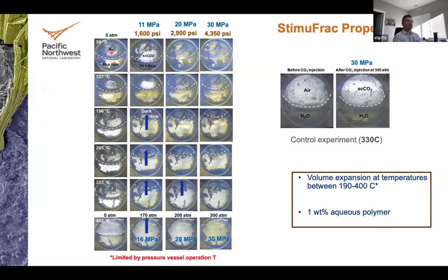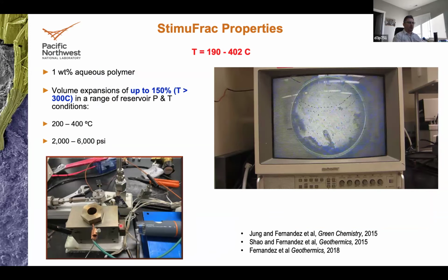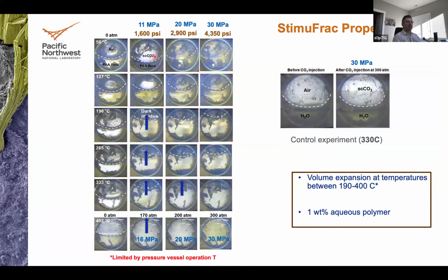So what you see here is not magic balls, but actually a window of the cell, as you probably saw here. This is the camera. You have the window here, another window here, obviously another one here, but we see a transmission video like the one that you see here. And then if you take multiple shots in the video, you can see what you see here. So this is the meniscus. This is the cell filled with slightly less than half of its volume with the fluid, the polymer solution.